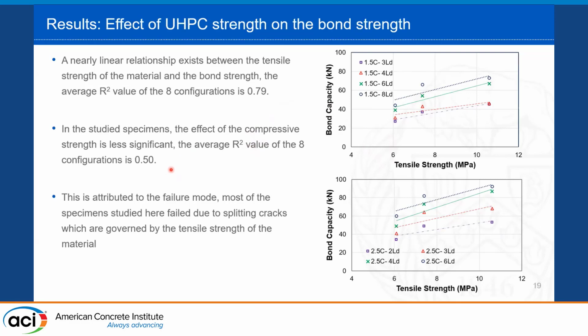So the reason for this behavior is due to the failure mode. Most of the specimens here failed by splitting failure. The splitting failure is usually governed by the tensile strength or the tensile behavior of the material more than the compressive behavior.